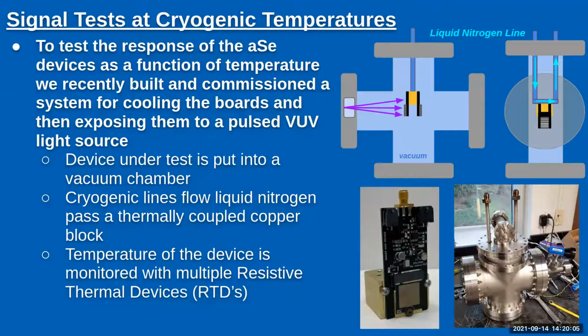So then we wanted to know, does selenium continue to give us a signal as we go down towards the temperatures that we care about for liquid noble detectors? So we recently built and commissioned a system that allows us to pass liquid nitrogen through a stainless steel line. We couple a copper block to that liquid nitrogen line and then put the board onto that so that we can gradually cool down and then let warm up these selenium devices without actually having to put them in a bath of whatever your favorite noble element is. And then we can expose that to direct VUV light. And we can also monitor the temperature of whatever's happening on our particular board using resistive thermal devices.